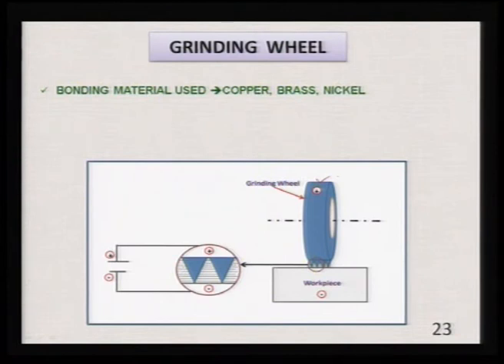Now, you can clearly see the role of the abrasive particles in surface grinding. Here these are the abrasive particles which are removing the material by abrasion, while this is forming the electrolytic cell, and because of this electrolytic cell formation, material is also removed due to electrochemical dissolution from this area, and these abrasive particles are removing the material by chip formation.